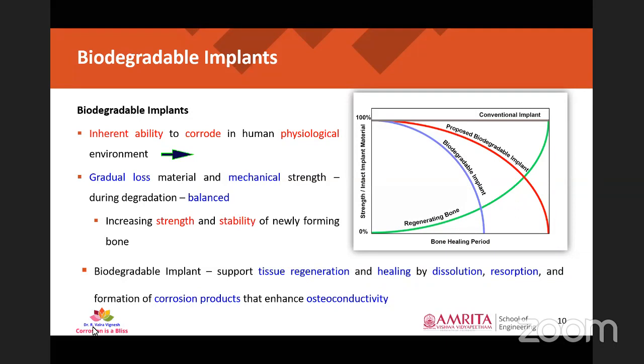So what happens is during the implantation period, the implant will just dissolve into the human body. But the problem with the currently used biodegradable implants is they just prematurely fail before the bone heals completely. So we have to develop a material that has an elongated period of time for dissolution, so that the bone healing period of the regenerating bone and the dissolution period of the proposed biodegradable implant meet at an exact point. So this is what we have to do.